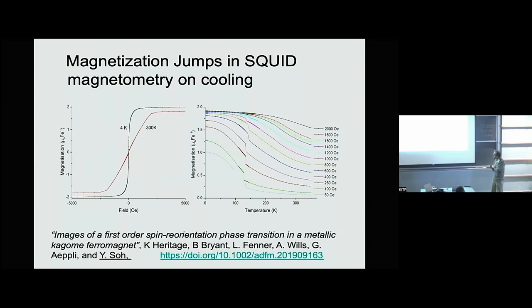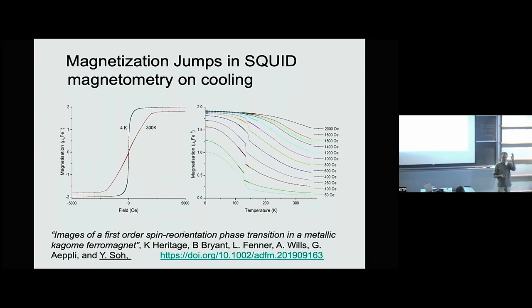There's actually a first-order phase transition terminating in a critical point in the field-temperature plane. So this is actually a rare instance of a magnetic analog to a liquid-gas critical point. What about the microscopic magnetism — what are the spin and orbit contributions to the ordered moment? This is important because for this material to be topologically non-trivial, you need some kind of spin-orbit coupling. If you don't have spin-orbit coupling, this is a boring material both from the point of view of the electrons and from the point of view of the magnons.